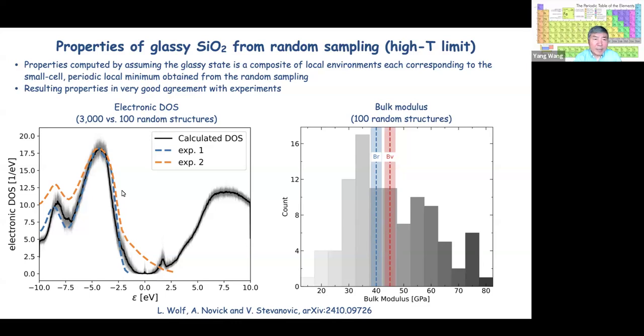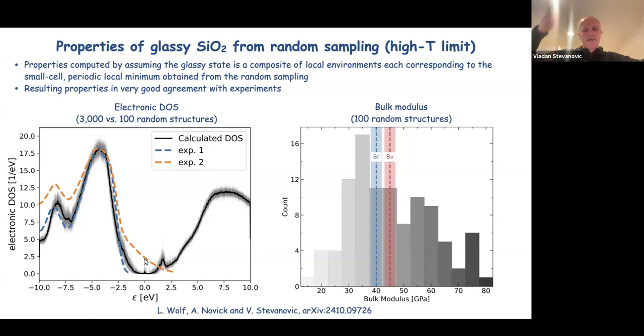Excuse me, why does the experiment say this is a metal? You have denser states. First, this is experiment. The blue one doesn't really. It's the orange. No, the orange one, yeah. The orange one, I think, is just sputtering. I still cannot find in that paper the reasons why it's different from the blue one. They grew a thin film just by sputtering, and I think it's not exactly a glass, so it has many more defects; it's basically a lower quality film. That's my interpretation. Whereas the blue one is again a film, but it's thermally grown somehow. I don't really understand how, but I think this is much closer to a glass than the orange one.